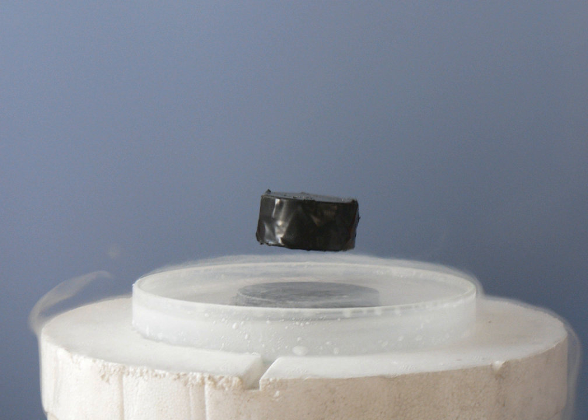This is because the Gibbs free energy of the superconducting phase increases quadratically with the magnetic field while the free energy of the normal phase is roughly independent of the magnetic field. If the material superconducts in the absence of a field, then the superconducting phase free energy is lower than that of the normal phase and so for some finite value of the magnetic field proportional to the square root of the difference of the free energies at zero magnetic field, the two free energies will be equal and a phase transition to the normal phase will occur.